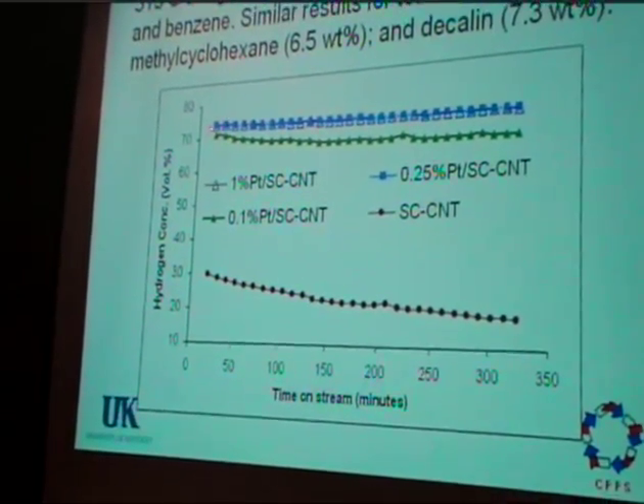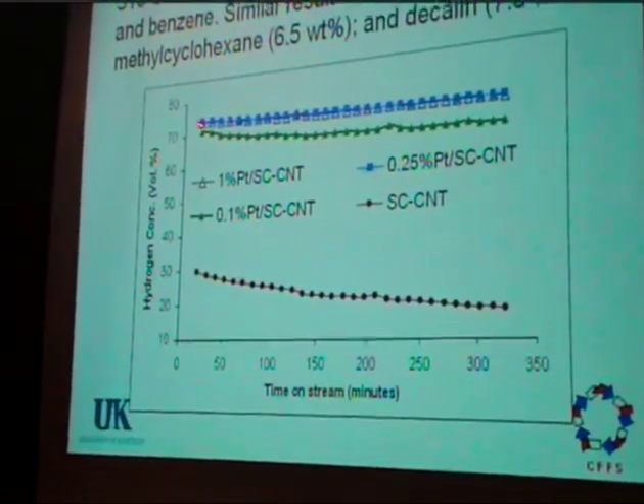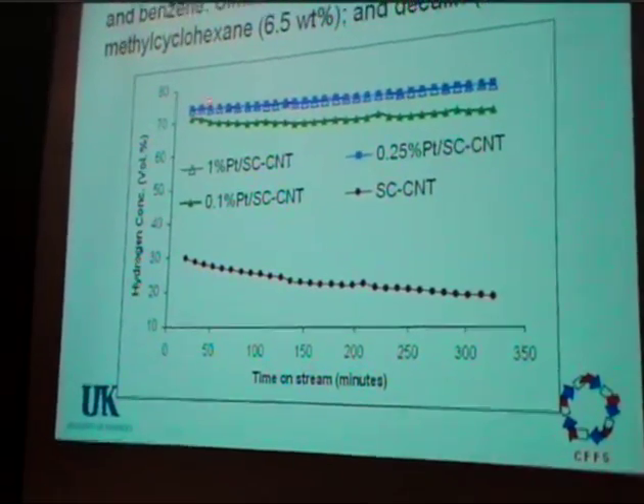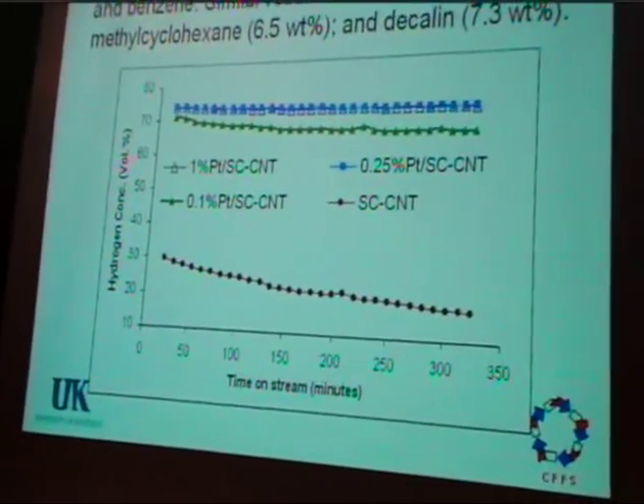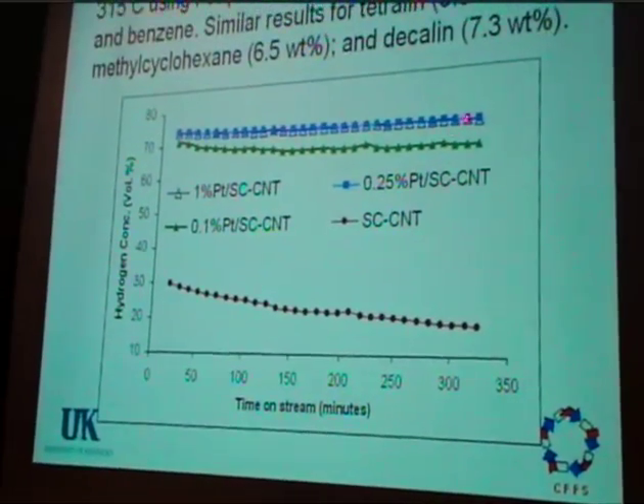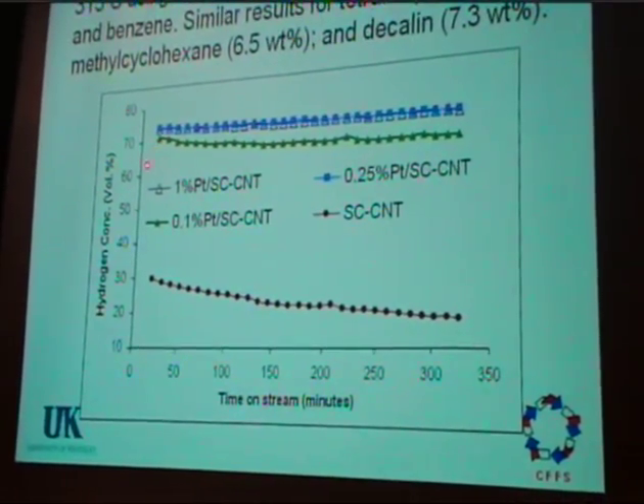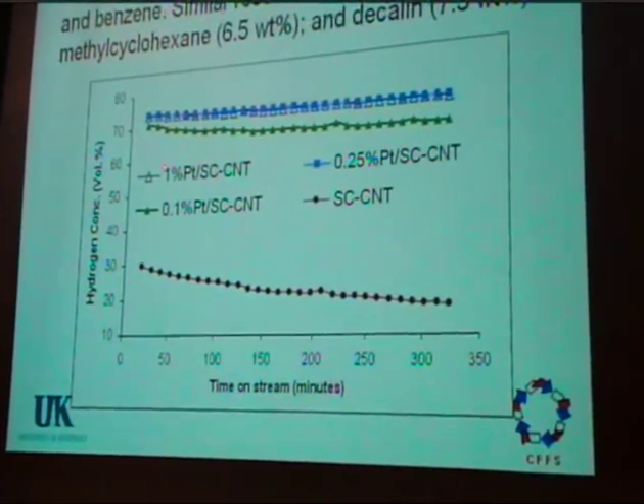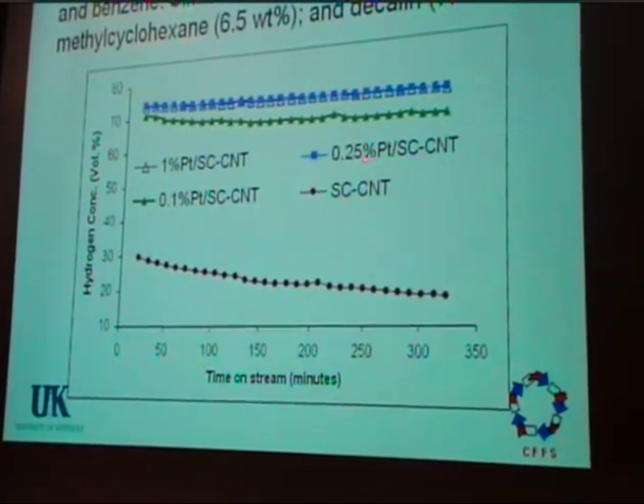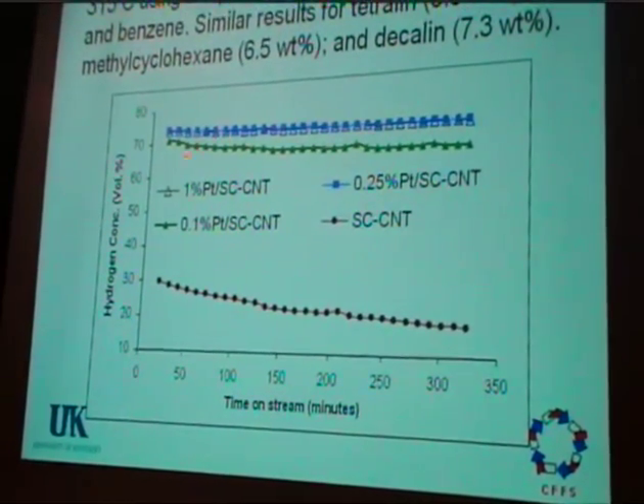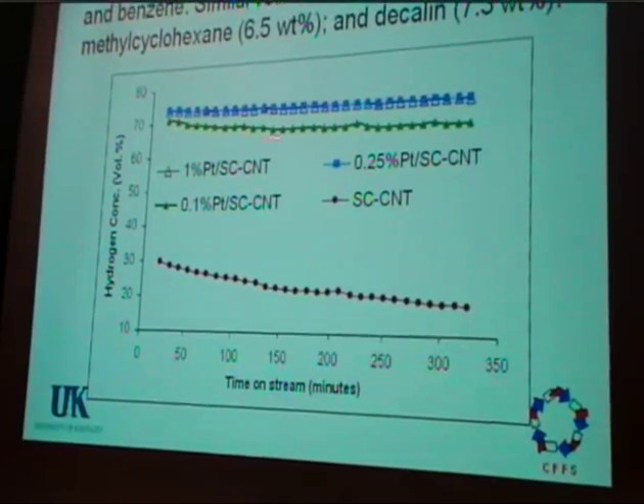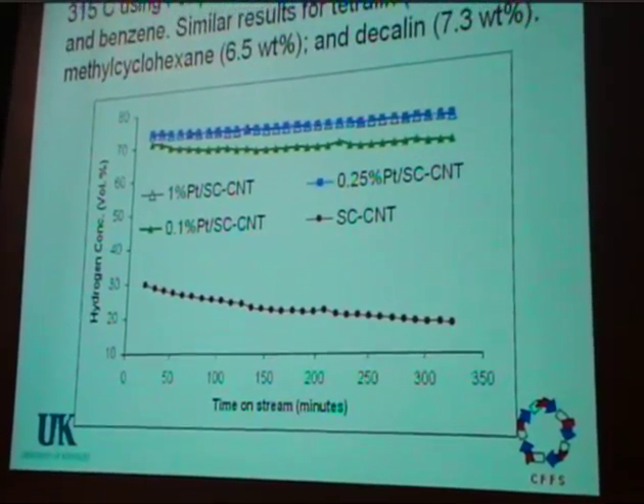You can see that you get complete decomposition, getting 75% hydrogen volume percent, so that's the right amount for total conversion. And you get this with 1% or 1/4% of platinum. You drop down to 1/10%, it does decrease slightly.